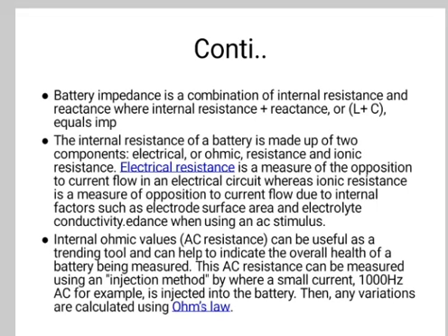Measurement with an alternating current, typically at a frequency of 1 kHz, may underestimate the resistance as the frequency may be too high to take into account slower electrochemical processes. Internal resistance depends on the temperature. For example, a fresh Energizer alkaline primary battery drops from about 0.9 ohm at low temperature, where low temperature reduces ion mobility, to 0.15 ohm at room temperature and about 0.1 ohm at 40 degrees Celsius.